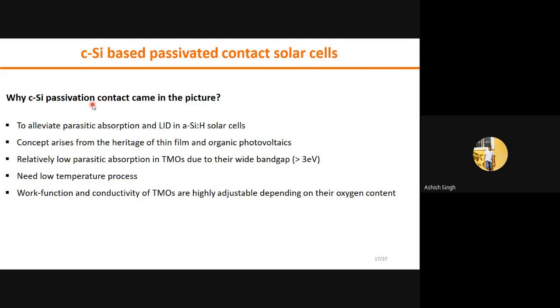So why did this passivated contact solar cell come into the picture? As we discussed in the previous slide, light-induced degradation in amorphous silicon and the parasitic absorption were the main reasons for that. So this passivated contact solar cell came from thin film and organic photovoltaic technology. People were already using transition metal oxide in organic photovoltaics as well as in thin film, and it's giving pretty good performance in that field. Due to the wide band gap material, it has low parasitic absorption compared to amorphous silicon, because amorphous silicon has a band gap in the range of 1.7 to 1.8 electron volt.